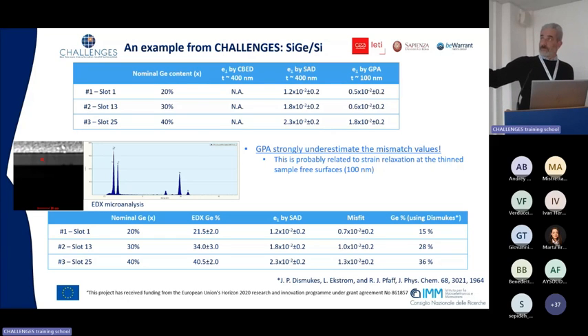This is again the mismatch measured by selected area diffraction. By imposing that your germanium is completely substitutional, you can, by calculation with elastic constants, evaluate the misfit, and so try to extract, by Vegard's law, this variation, the germanium concentration corresponding to this strain measurement. In the case of the first sample, we obtain 15% compared to 20%, but in this sample, 28 against 30, 36 against 40. So it's not too bad, in my opinion. In this case, less than half.